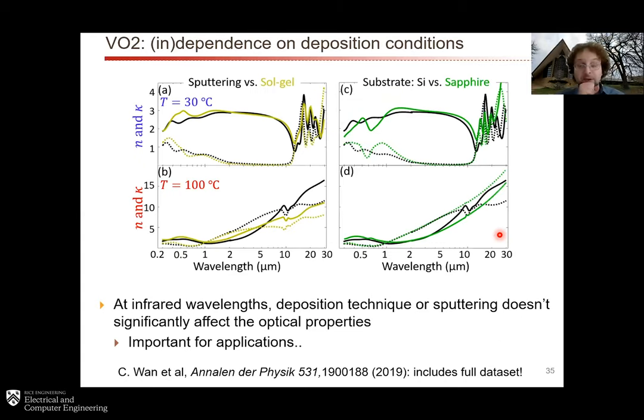Now, as I mentioned, VO2 is famously finicky as far as its dependence on deposition conditions, on even who deposited it, what technique did you use, what is the substrate, what is the thickness, and so forth. And so we wanted to get to the bottom of that. So we did a lot of comparisons, a couple of which are shown here. This is again in this paper.